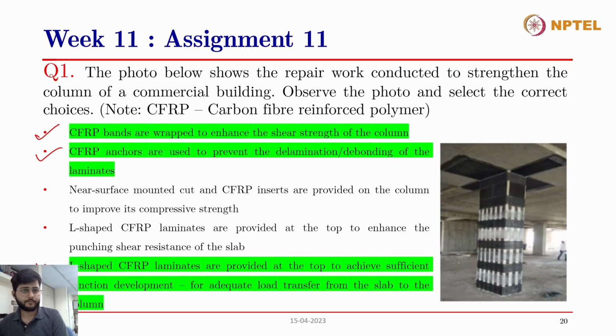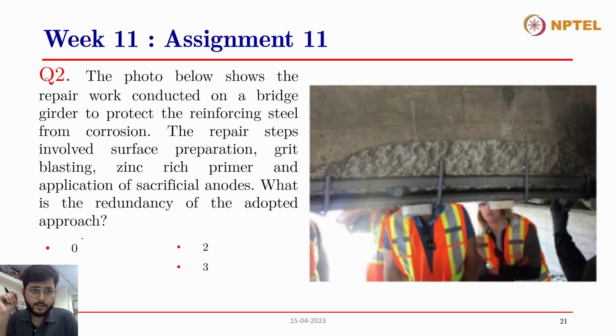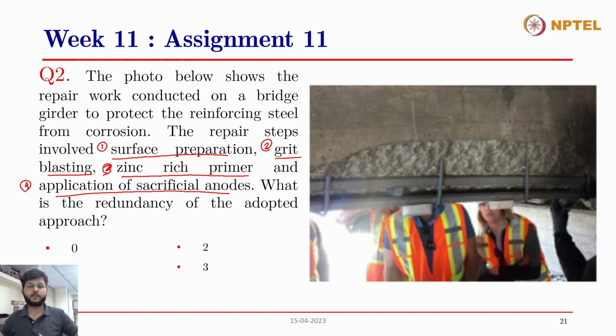All right. Moving on to the second question. The photo below shows the repair work conducted on a bridge girder to protect the reinforcing steel from corrosion. The repair steps involved surface preparation, which is one of the repair methods. Then there is grit blasting. Then there was zinc rich primer. A primer coat was applied on the repair surface, and finally application of the sacrificial anodes. So these were the repair steps that were carried out in this image.